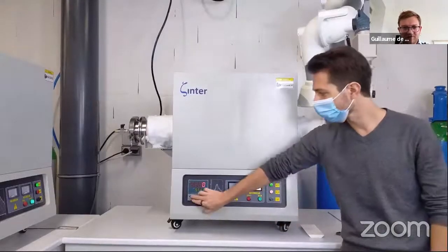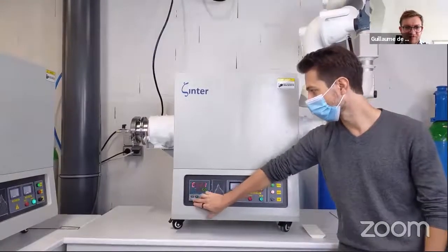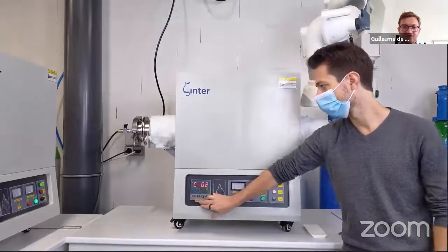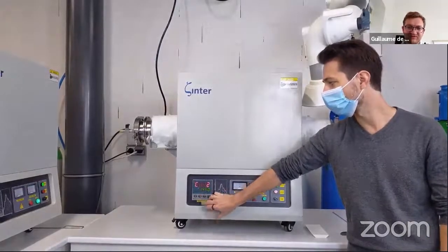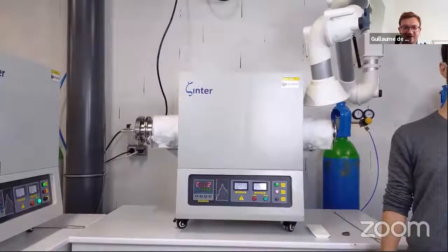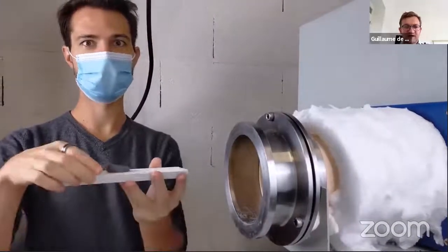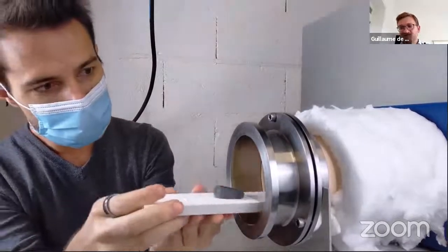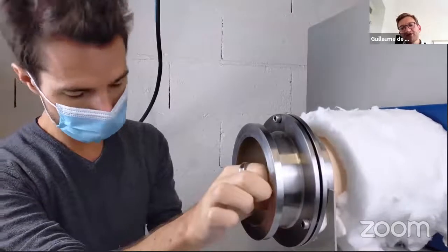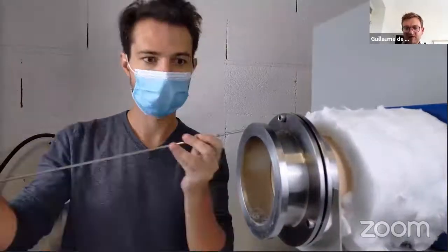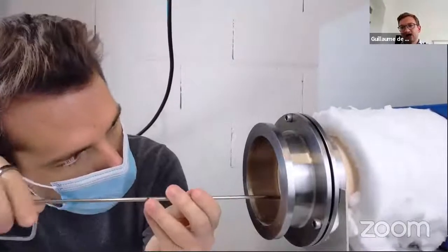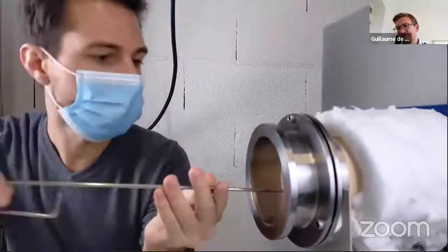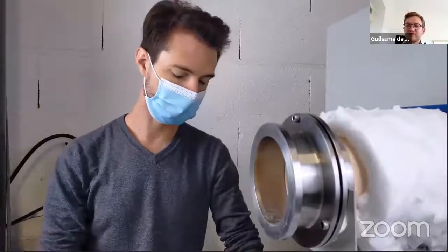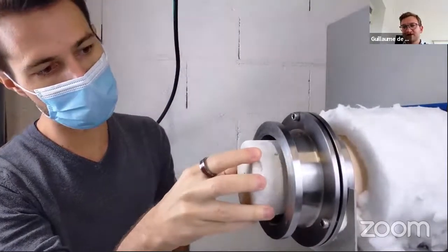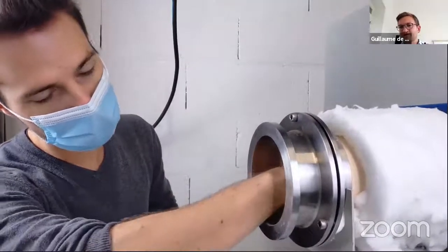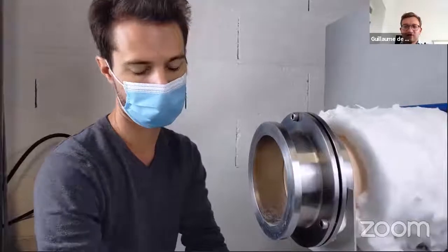So here's a quick demo of sintering, how it's programmed, and how we put the parts. So here is the programming. The programming has already been done, so we just check it. We don't need to modify it actually. And then we just put the parts on plates, and we insert the plates in the tube furnace. Here it's a tube furnace. The big interest of tube furnaces is you can use them both for ceramic and metal. It's very easy to put the tube furnace under neutral gas, which is a bit more complex for a chamber furnace. So when a customer wants to do both materials, we usually advise to use a tube furnace, and if he wants to do only one material, he can use a normal furnace.